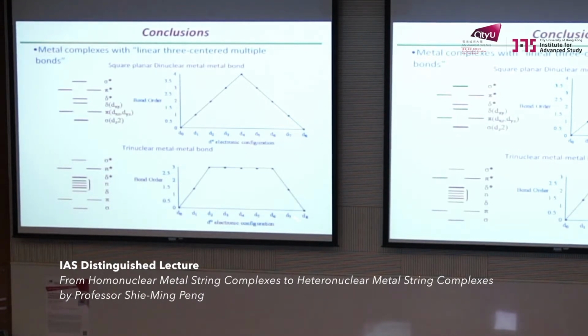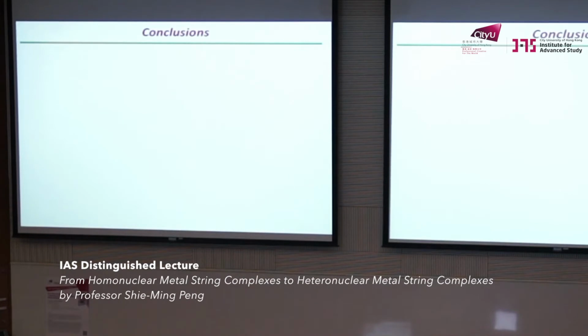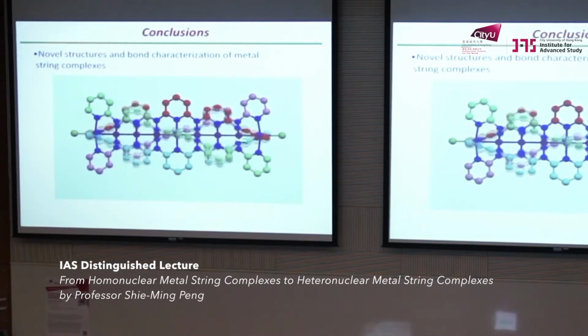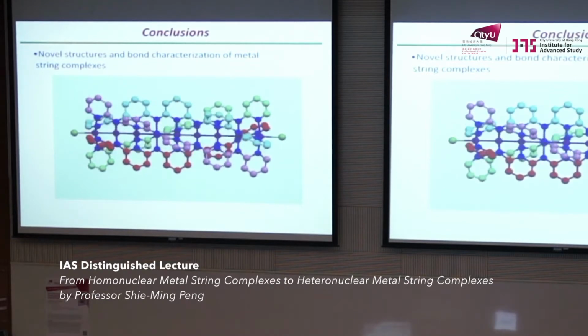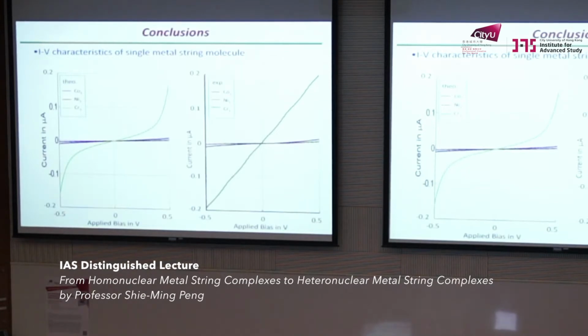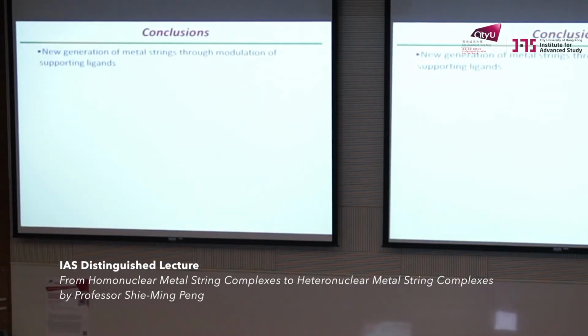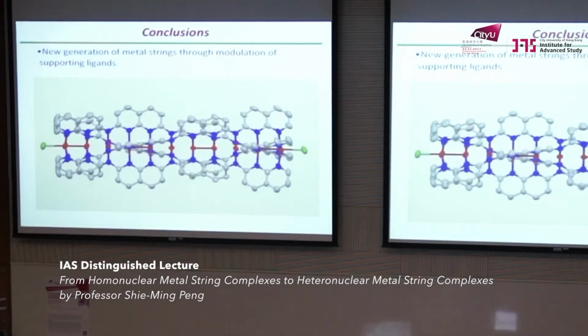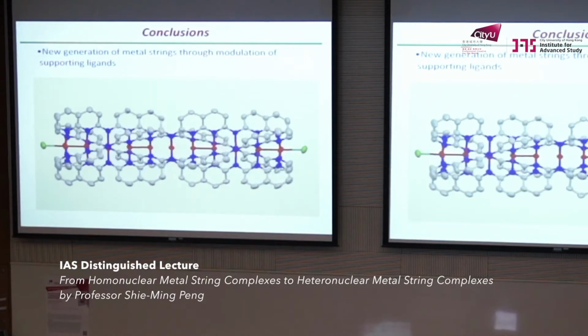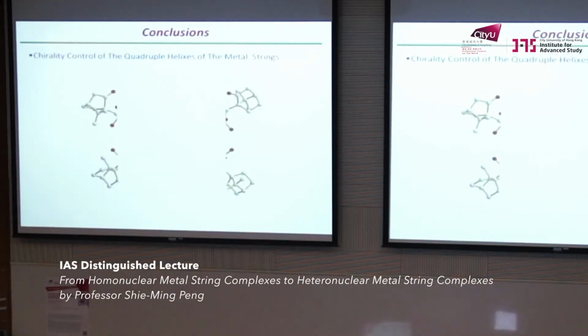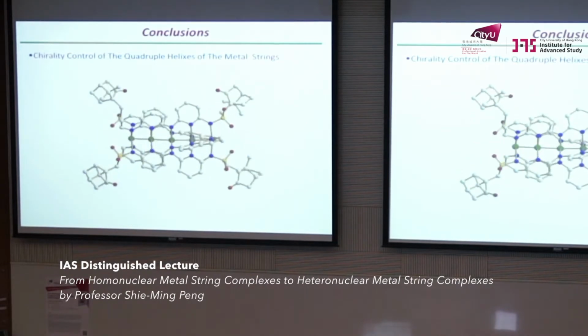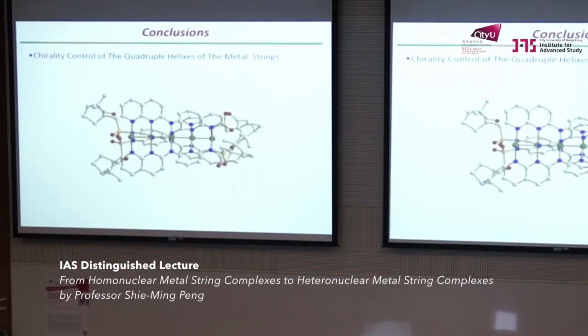This is the simplified three-center one with our helical structure: 3 bonding, 6 non-bonding, 3 anti-bonding, as I show you in this part of the structure variation. We extend this trinuclear one to oligonuclear, a really unique metal string complex, and claim it as the molecular metal wire. We can measure their single molecular conductance, even simulate them. And we have the new generation introducing the mixed valence unit to increase the conductance. And we can also control the chirality of this quadruple helix.